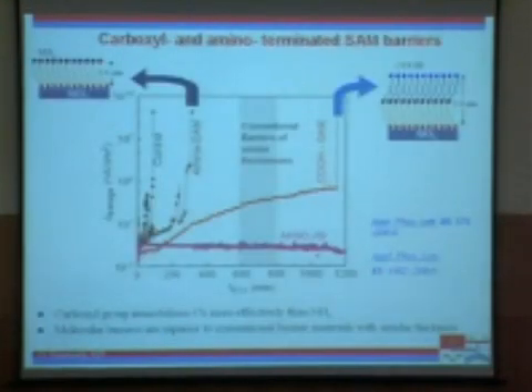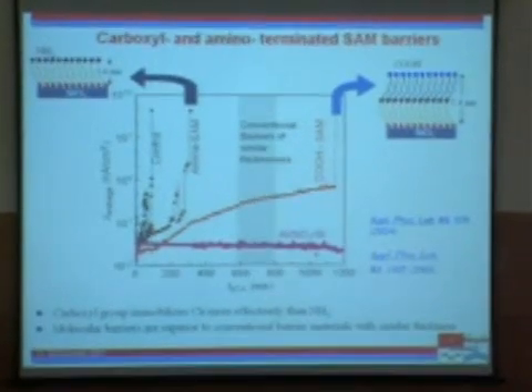and also the leakage currents are much smaller. And to give you a perspective on how good these are compared to the barriers currently used in devices, again leakage current as a function of time, you can see without any barrier, it's pretty bad. And if I have conventional barriers of similar thicknesses, like these two molecular barriers, you can see if I have an amine terminated layer, I get improvement, and if I have a carboxyl terminated layer, I get a really very large improvement. In fact, it's better than conventional solutions of similar thicknesses, and this is without any optimization.